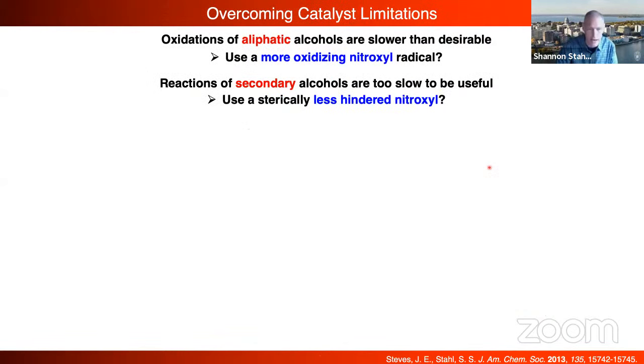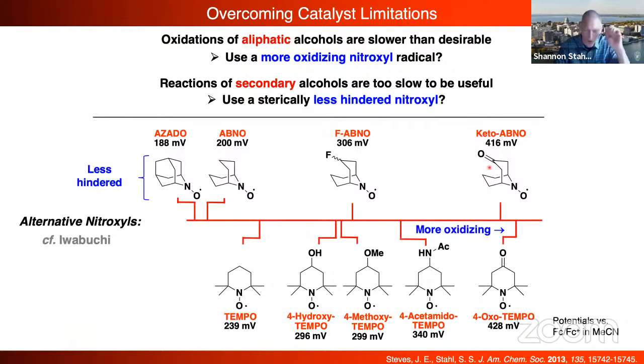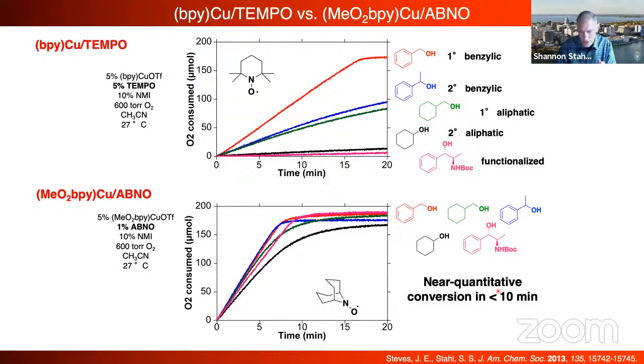Okay, I think I want to speed up a little bit through the synthetic scope. So I'm going to maybe go a little too fast through these next couple slides. We wanted to develop a better catalyst because we wanted to be able to oxidize secondary alcohols. We thought about changing the redox potential of TEMPO. Turns out if you use a stronger oxidant in the TEMPO, it's no longer a good ligand. And in fact, it works worse. What works best is actually changing the sterics.